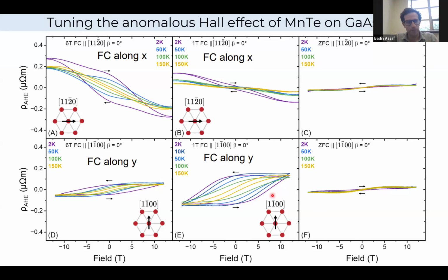Now, unfortunately, the lattice parameter of strontium fluoride is smaller than the lattice parameter of manganese telluride, so it will strain manganese telluride in the opposite direction to gallium arsenide. So that wouldn't necessarily rule it out, and I think to really rule it out, you have to find a third substrate that has a lattice parameter that's slightly larger than manganese telluride. Maybe barium fluoride would work. So that's a good idea actually, and it's something we're currently developing, but not on strontium fluoride because that would not be the right substrate. Okay, I see. Thank you.